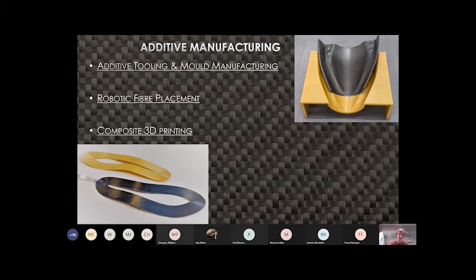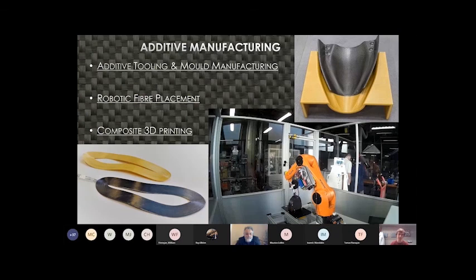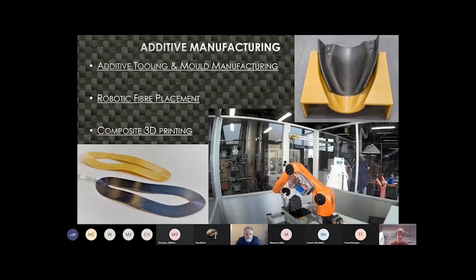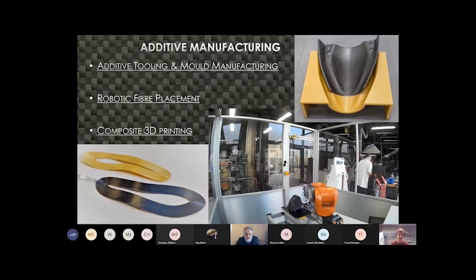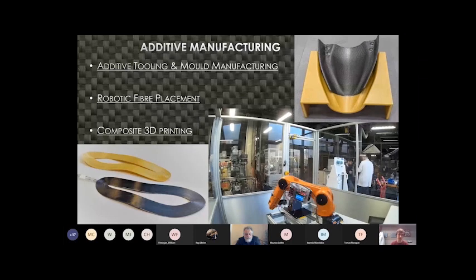So this would be a PEI or a PEEK mold printed on a large format printer, which we have several of here in the mechanical engineering department. And then you can use that to mold your traditional composite on top of, whether it's hand layup or ATP, and combining that then with other technologies which I in particular developed during my PhD several years ago. We're able to print the mold and then use an additive manufacturing type of system mounted onto a 6-axis robot, and we're able to print relatively complex curves directly onto the mold, and that means that if we want to do 1 or 5 parts, we can do very low cost, short run batches of these parts.